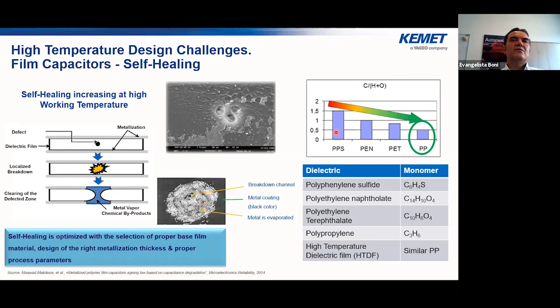The effective behavior of self-healing is strongly dependent on the base film material that is used. Here we can see a graph with some bars, and the bars indicate the ratio between the number of carbon atoms of this film dielectric and the number of hydrogen and oxygen atoms. We can see that the lower the number, the better the self-healing characteristic. From the chemical point of view, of course, this is not the only reason for good self-healing, but it is an important variable.